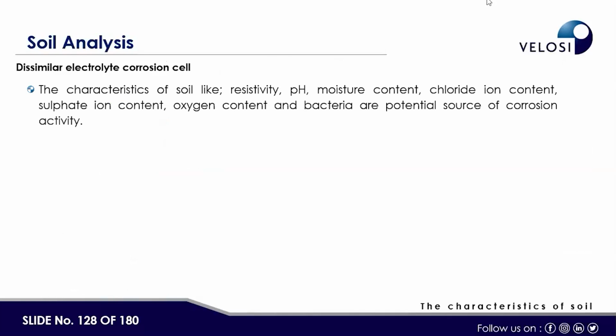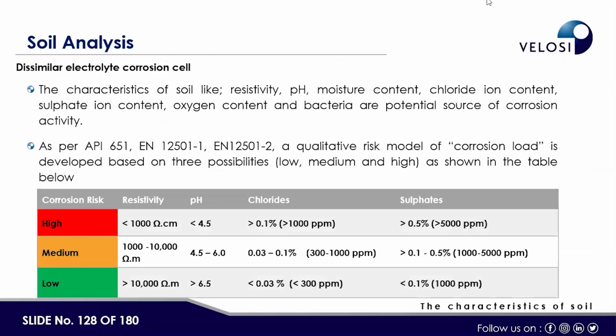Next, apart from the resistivity, you need to know the pH, moisture, chlorides, sulphates, and other bacteria. If we combine all these things, an area with less than 1000 ohm-centimeter, pH of 4.5 or less, chloride content greater than 1000 ppm and sulphate greater than 5000 ppm is a very aggressive, very corrosive soil. It is near seawater, the coastal environment, marshy areas or sabkha soil. Whereas soil between 1000 and 10,000 with relatively higher pH and lower chloride will be high, medium and low, so we can categorize our soil.